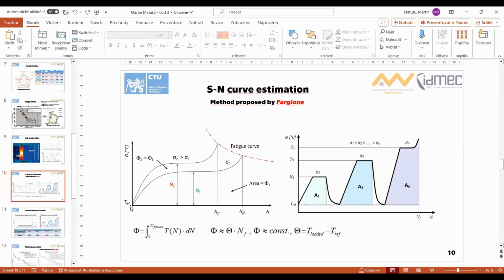This is the temperature evolution from the beginning to the failure of the specimen on the single value, but this is the self-heating step test, and we were trying to find out if the limiting energy from the single level test and from the self-heating step test is the same if you do the summation. And by this simple assumption, we could potentially estimate the number of cycles to failure.